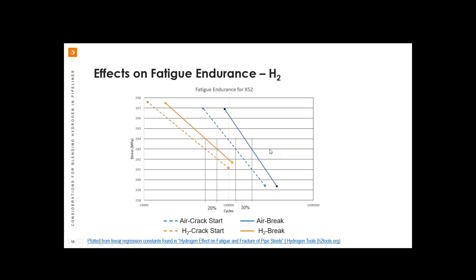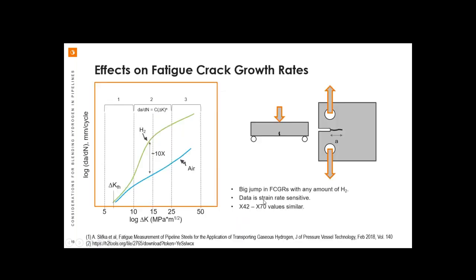But if it does, we see two important bits of data. One is that our overall fatigue life drops substantially. This is a log plot, so it's a big drop. And the other is that the percentage of this fatigue endurance life is actually smaller. So we have a little less cushion. Only 20% of the life is with a fatigue crack growing versus 30% as before.